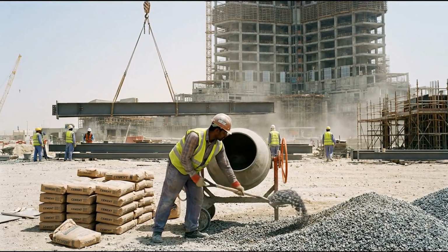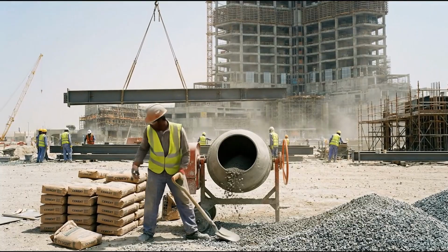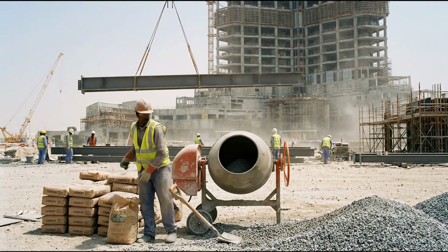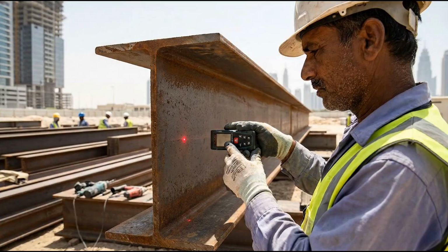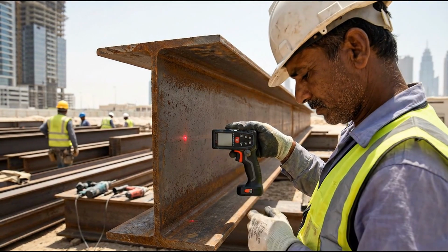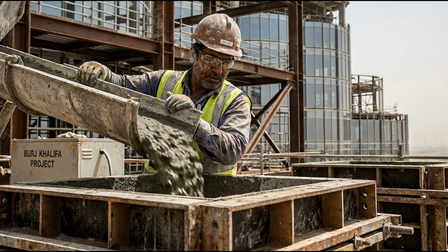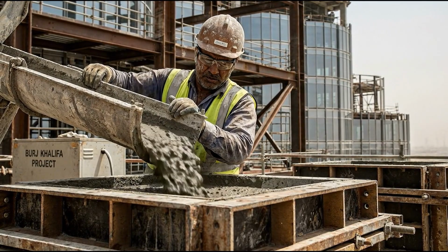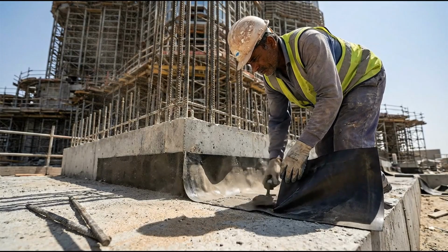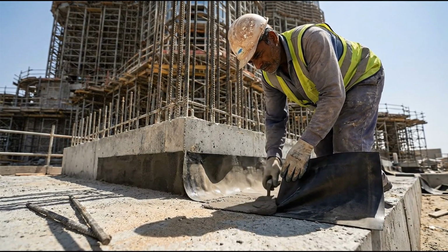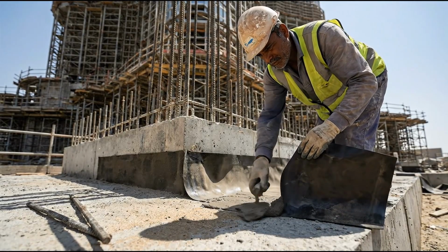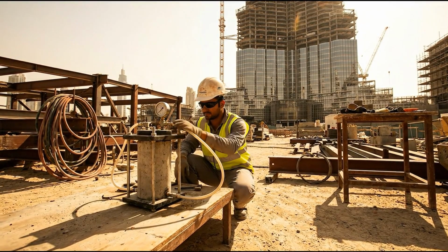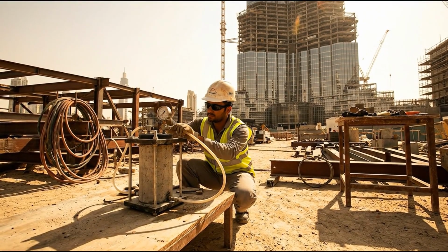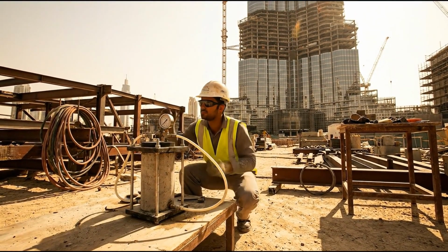The team approached this on multiple fronts simultaneously. The concrete mix itself was the first line of defense. The same high-performance formula used in the piles, low water-to-cement ratio, silica fume, chemical admixtures, created a matrix so dense that water and dissolved salts could barely penetrate it. Permeability tests confirmed that this concrete was many times more resistant to chemical attack than standard mixes.